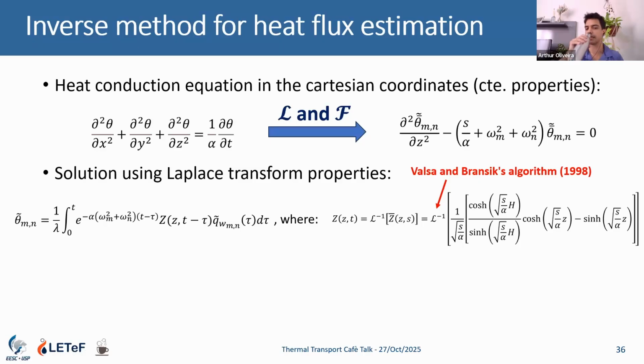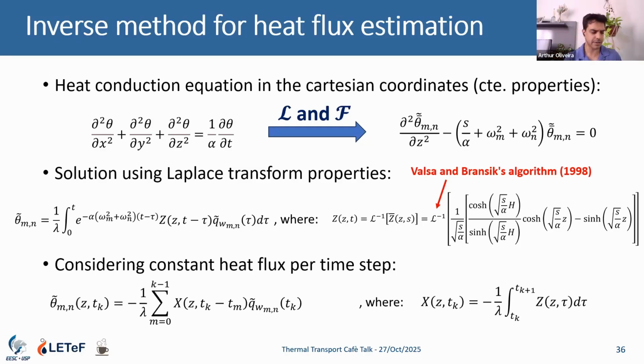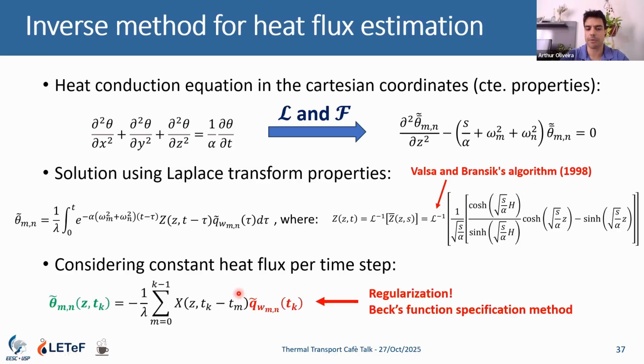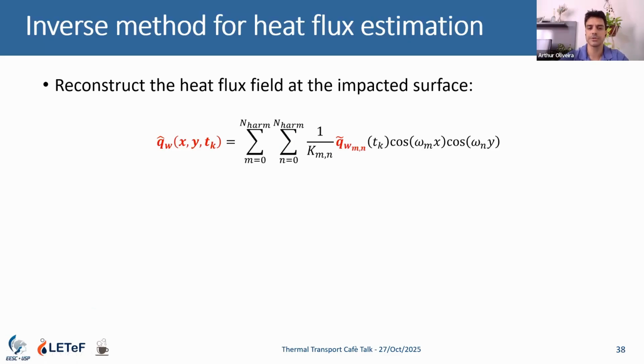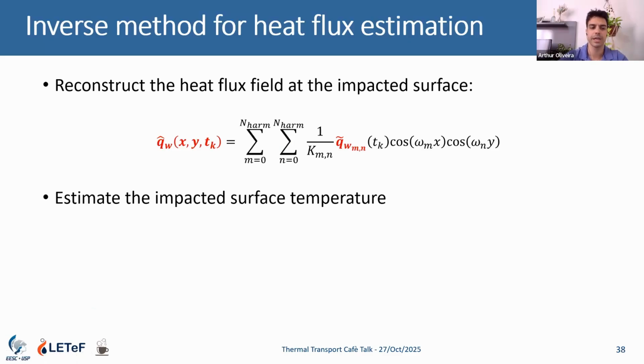And we discretize that by considering a constant heat flux profile per time step. The difference now is that we are estimating the heat flux harmonics in Fourier space. So we need to go back to the real space using a Fourier cosine transform in our case.